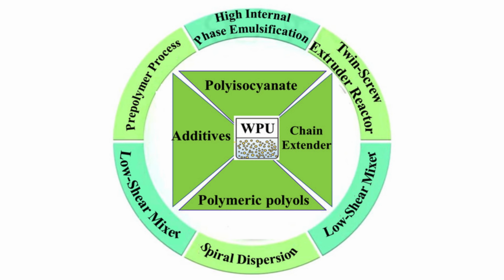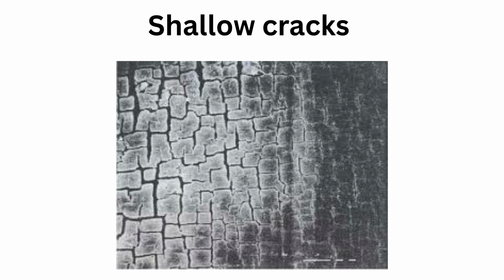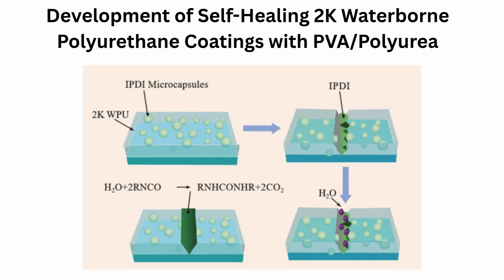However, WPUs are easily damaged by external conditions, resulting in cracks or even fractures, which seriously affect the various properties of waterborne polyurethanes. In dry environments, rapid moisture evaporation can induce crack formation, while in humid conditions, cyclic moisture absorption, swelling, followed by drying shrinkage, leads to fatigue cracking. Furthermore, elevated temperatures accelerate both hydrolytic and oxidative degradation of polymer chains. Additionally, prolonged mechanical stress, or UV exposure, may cause chain breaking, resulting in crack initiation.